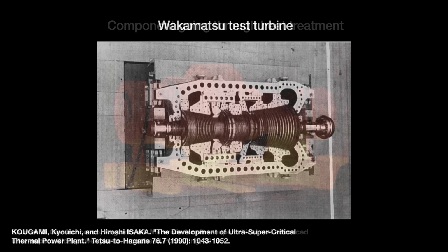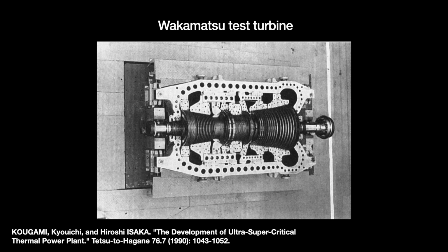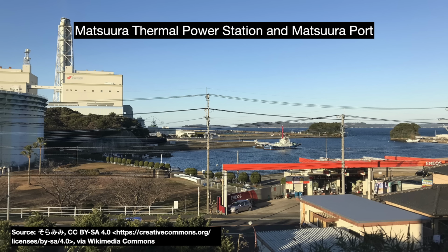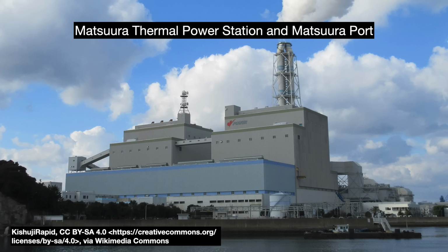Mitsubishi Heavy Industries used TMK1 for the rotors of the Matsuura thermal power plant in Unit 2. It began operations in 1997. At 1,000 megawatts, it was the first large-scale ultra-supercritical steam plant. With operating steam pressures of 24.1 megapascals and temperatures of 593 degrees Celsius, its thermal efficiency of about 42% broke new ground. Recall that supercritical plants had about 34 to 35% efficiency.